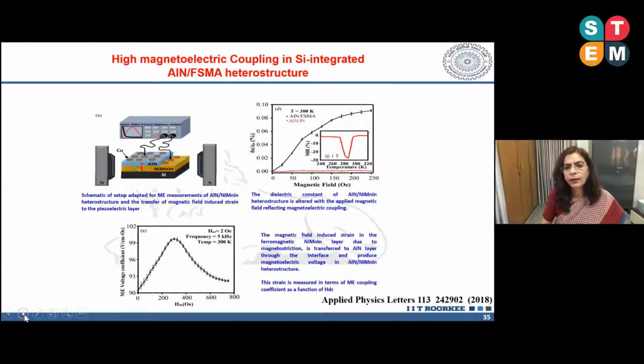Next please. So here we have tried to see the dielectric constant change versus magnetic field, and then the value of alpha versus H. Alpha was found to be higher in this case—that coupling coefficient is the magnetic field induced strain in the FSMA layer due to magnetization in the transferred aluminum nitride layer through the interface, and it produced a magnetoelectric voltage in the aluminum nitride-FSMA heterostructure. The strain measured was higher compared to our previous work with the PZT structure.